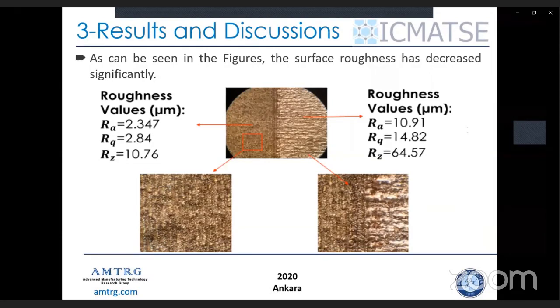Roughness values of as-built surface RA, RQ, and RZ was 10.91 micrometers, 14.82 micrometers, and 64.57 micrometers respectively. And when we check the laser polished surface, RA, RQ, and RZ was 2.34 micrometers, 2.84 micrometers, and 10.76 micrometers respectively. And actually, besides, we can observe the layer thickness of the parts from the as-built surface and laser hatch distance, which I said before, it is the distance between two laser tracks, can be observed from the laser polished surface in the figures.